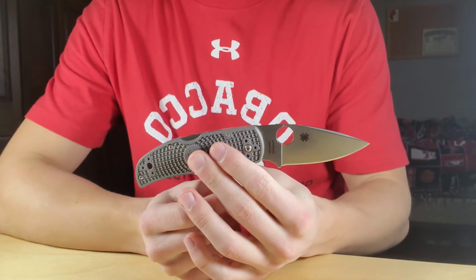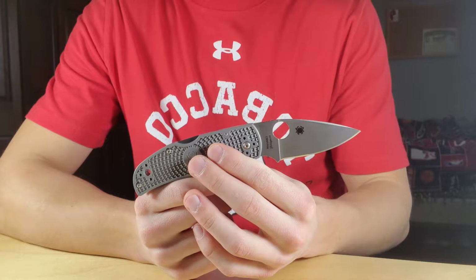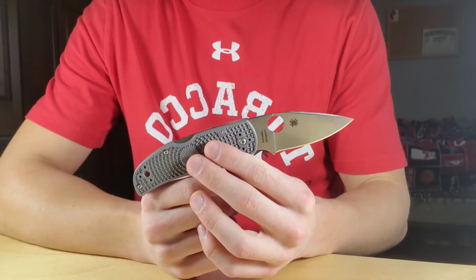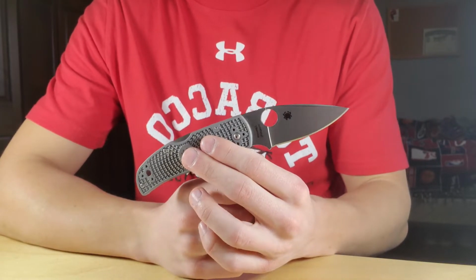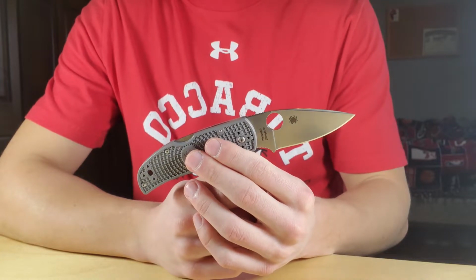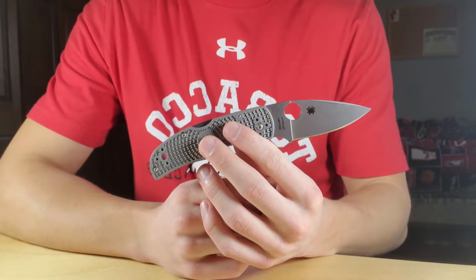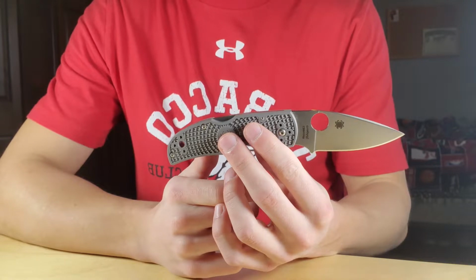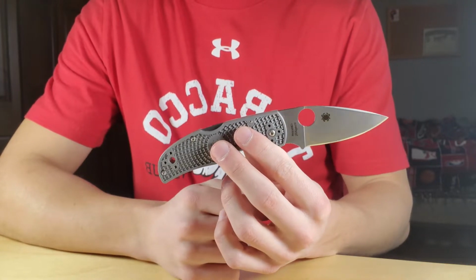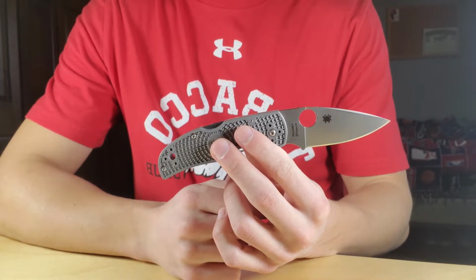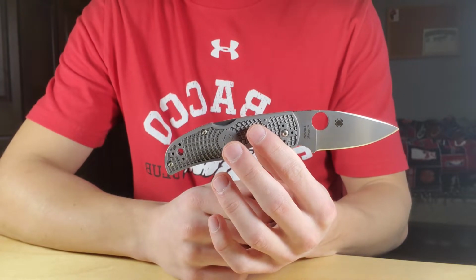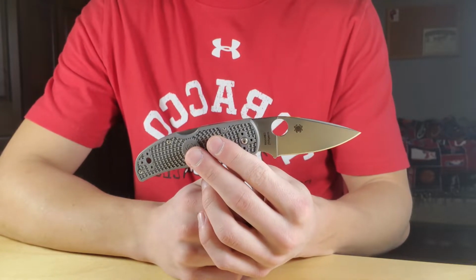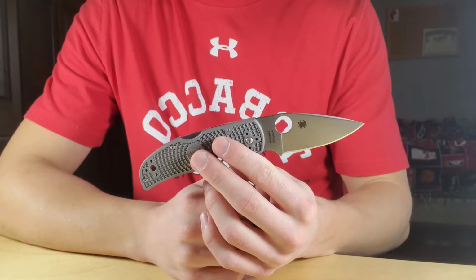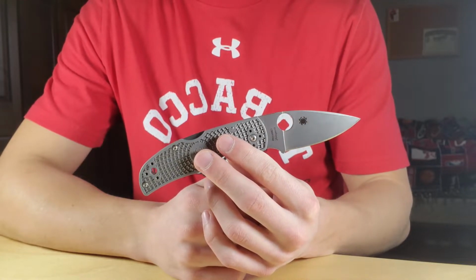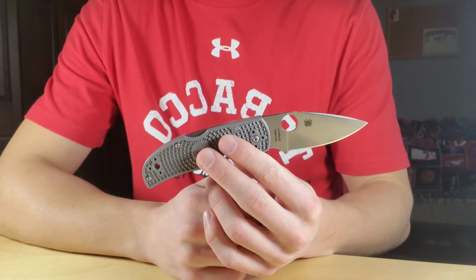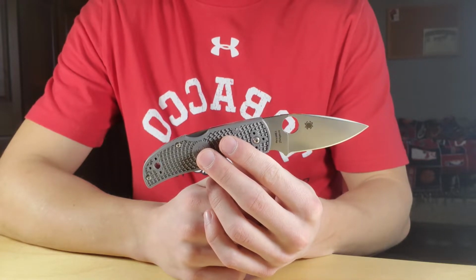This was also seen in the original edge retention testing I did on this Native 5 here in Maxamet, the original one that I did all of the Maxamet experience with. This thing's sitting at 69.2 HRC with those super hard tungsten and vanadium carbides. When I initially edge retention tested it, I finished it with the 1200 and 1600 grit ceramics, which I believe are an aluminum oxide based stone. And obviously aluminum oxide is not hard enough to abrade the carbides in there.